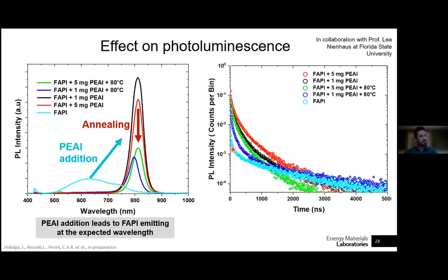In non-passivated formamidinium lead triiodide, we have the fastest dynamics. Upon introduction of phenethylammonium, we slow down this recombination, but again, annealing fastens it up. And these dynamics could explain the enhancement in open circuit voltages that we saw in passivated films.